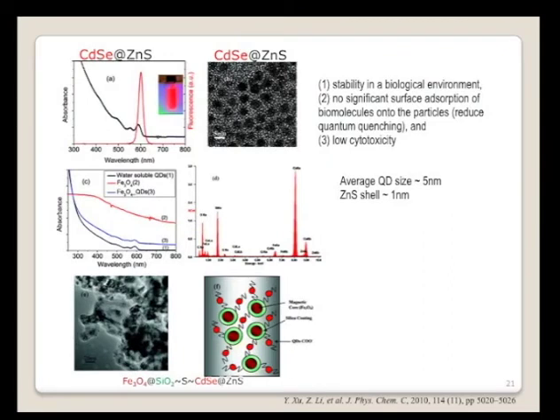We still need to modify another part, the quantum dots. The quantum dots still need to be modified. Here we use cadmium selenide. Cadmium selenide itself is not toxic, but in the biology environment, it can release cadmium ions that are toxic. So we have to make some treatment. So we coat it with zinc sulfide. This coating can improve the stability of this nanoparticle in the biology environment.